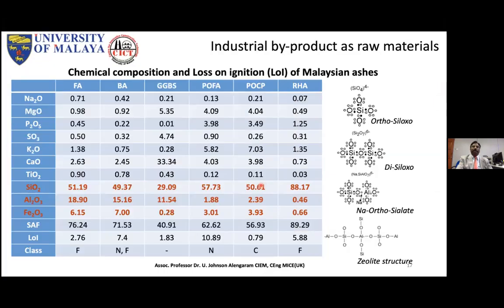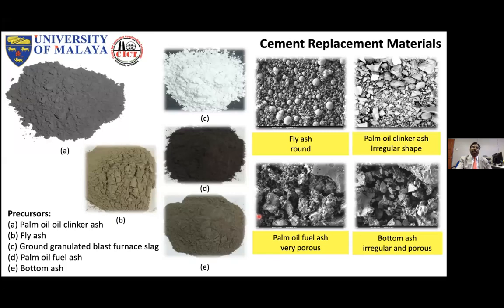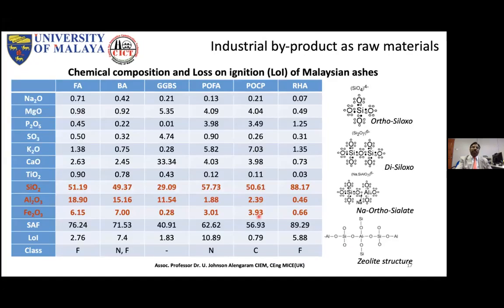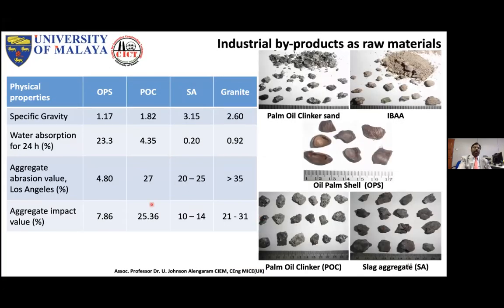So if you look at this, LOI is only 0.78, because it is burnt at probably 600 or 400 degrees Celsius. So after burning, what you get is the clinker. Therefore, this is a pozzolanic plus filler. Also, if you see the physical properties here, this clinker here, 1.8 is the density.